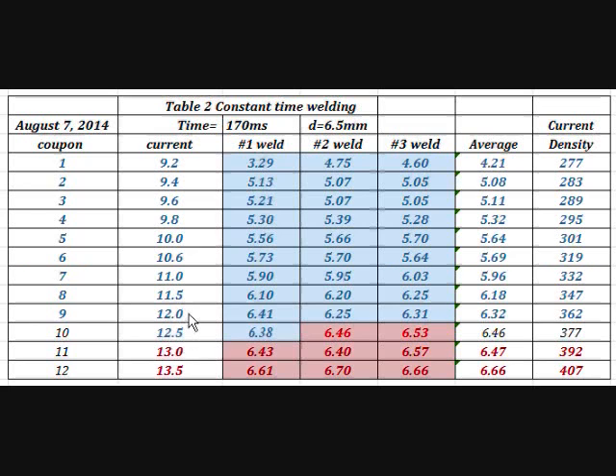All the way to about 12.0 kiloampere. You see at this point, this nugget is about the same size as the weld cap diameter. Next one is 12.5 kiloampere. All of a sudden, I have one solid state weld and two expulsion welds. The average is 6.46.